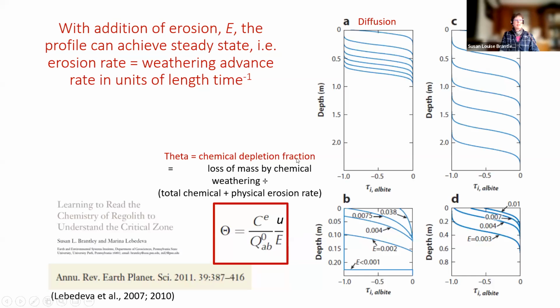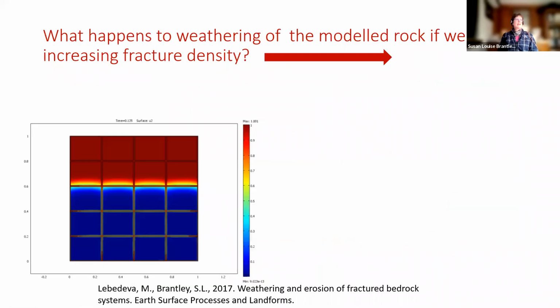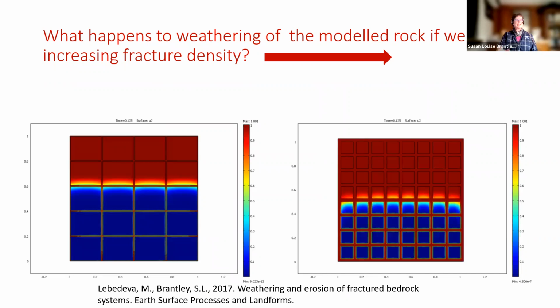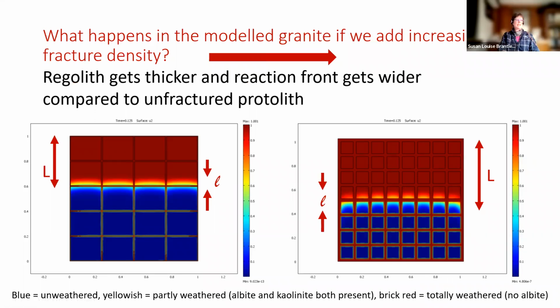So people talk about the chemical depletion fraction, or theta, and it's how much is dissolved away versus how much is eroded away. So the chemical depletion fraction is just related to this idea. You either lose all the albite in the subsurface or you have some of it that makes it up to the top because the erosion rate is so fast. Well, you can play all sorts of games with these. You can put fractures into the system. And here the blue is unweathered. The red brick colored is weathered. The colors in between, there's still some albite in here dissolving. These are fractures. And what you see, depending on how you set up the model, is when you increase your fracture density, you actually get deeper weathering and you get wider reaction fronts.